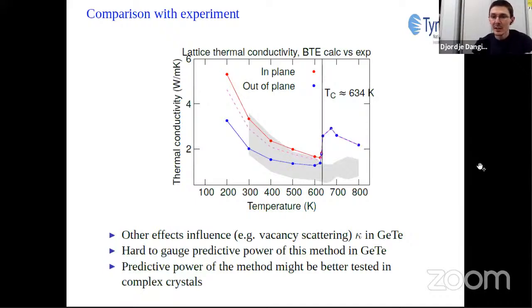But it is hard to gauge the predictive power of this Green-Kubo approach due to other effects that influence lattice thermal conductivity in germanium telluride much more, such as, for example, vacancy scattering. The predictive power of this method might be better tested in more complex materials with more atoms per unit cell that exhibit amorphous-like lattice thermal conductivity.